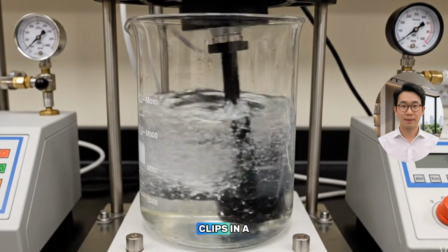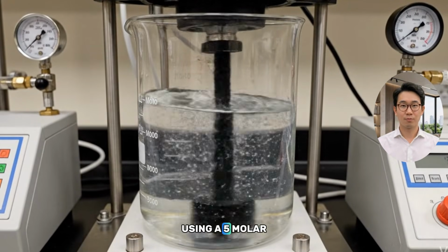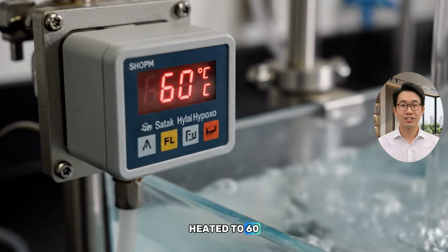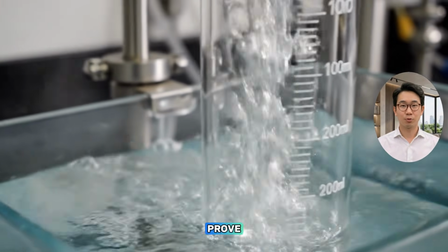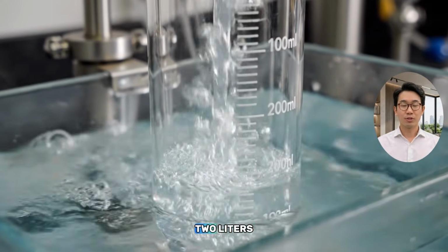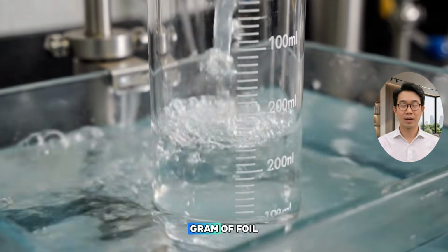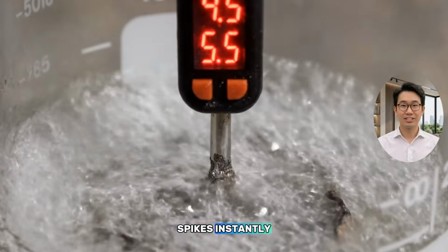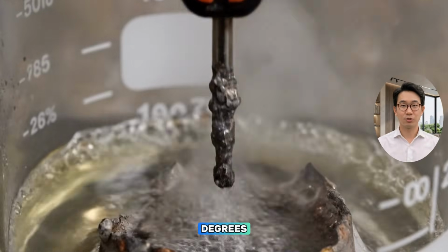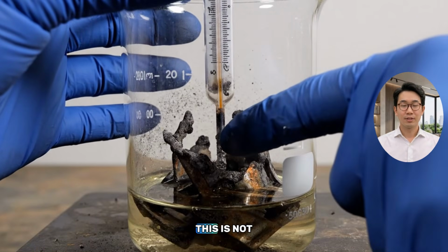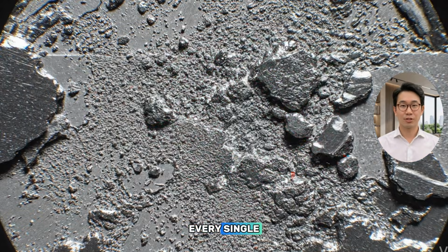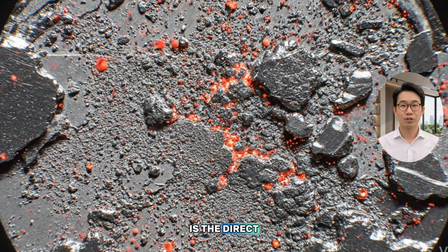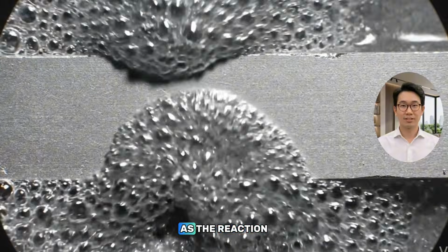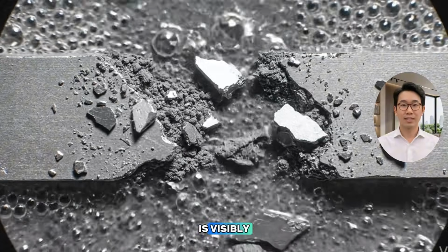kitchen clips. In a controlled lab setting using a 5 molar sodium hydroxide bath heated to 60 degrees Celsius, measurements prove that aluminum can pump out 0.2 liters of hydrogen gas for every single gram of foil. The temperature spikes instantly, frequently jumping more than 10 degrees in a matter of minutes. But remember, this is not free energy. Every single joule of that heat is the direct result of oxidizing the aluminum. As the reaction burns on, the metal is visibly eaten away.